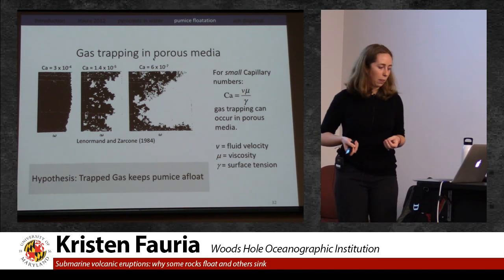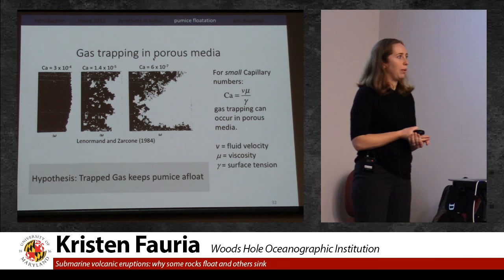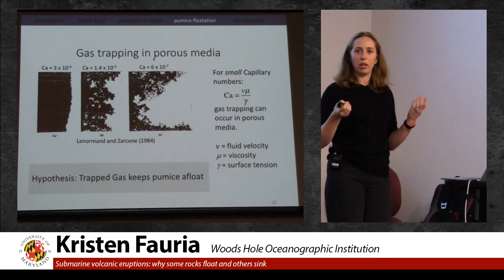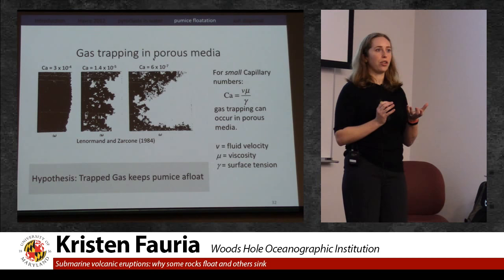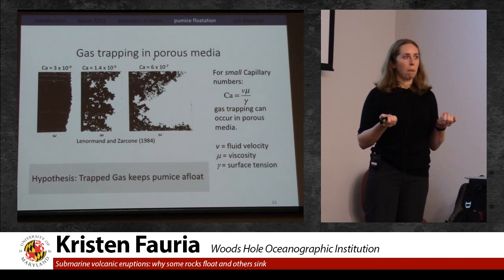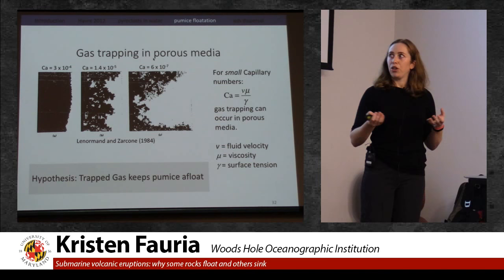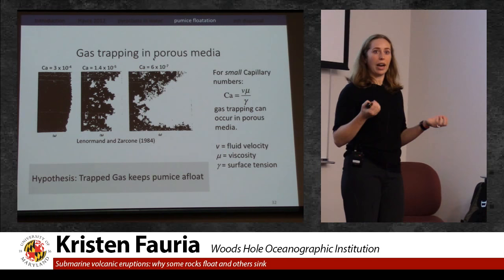To test this idea, we conducted a series of experiments where we put pumice in water. We heated some of the pumice up first. We left others at room temperature, and we let it sit. After a couple days, we took the pumice out, and we really quickly encased it in wax. The wax just preserved that internal distribution of fluids inside the clast. Then we put the pumice into an X-ray microtomography machine at Lawrence Berkeley National Lab to image the three-dimensional distribution of the gas, the water, and the rock.